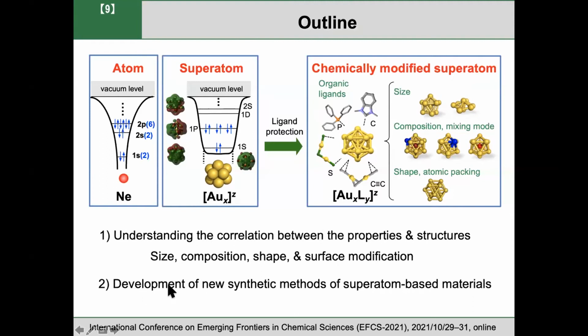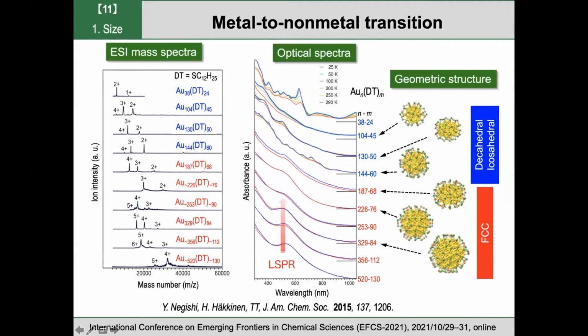Let me first start with the size effect on the properties. Here is a series of mass spectra for the thiol-protected gold clusters. DT means dodecanethiol. So we can determine a chemical composition like this by using ESI mass spectrometry. And then we measured optical absorption spectra for these clusters. So here are the optical absorption spectra for the series of clusters we isolated.